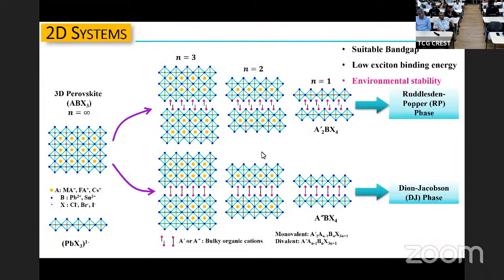To form this, as I told you, structurally it won't be stable unless I put in the yellow dots. Those are the ones that go to the cube center and stabilize the structure. I told you that I'm going to put long molecules here to split it open. But it's not the interaction of that long molecule alone, but the fact that there's nothing to stabilize this 3D structure. So the 2D layer can form, but in order to make the 3D, I need these yellow ones to stabilize the structure. When I don't put in any yellow dots, and put only the long units, I get this. But if I now control the ratio of this to that, I get a different number of layers. That's how you try to control it.